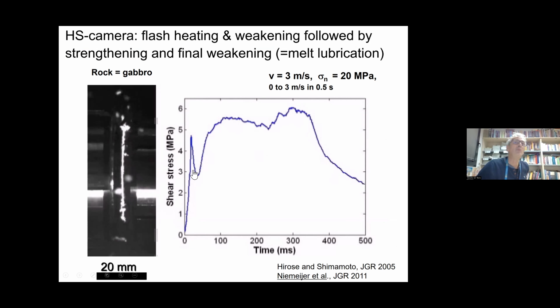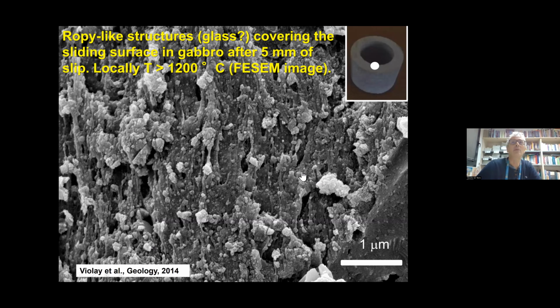So the initial weakening, but then there is the formation of these continuous patches of melt that impede a nice lubrication. It's a sort of mixed lubrication of the experimental fault, and then until there is a continuous layer of melt, which goes to melt lubrication. So we studied this thing quite a lot.